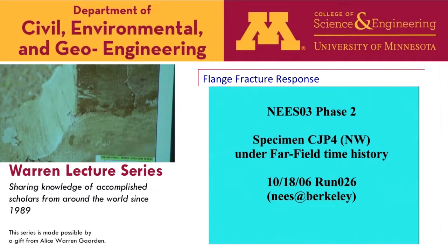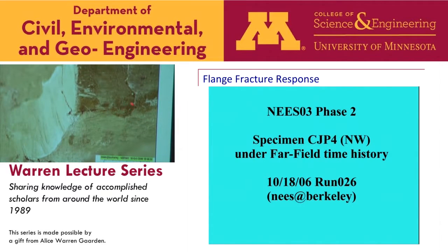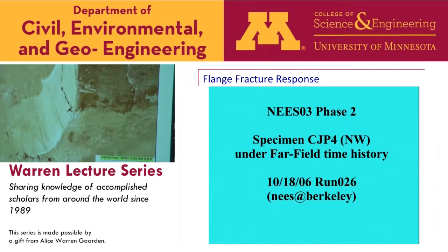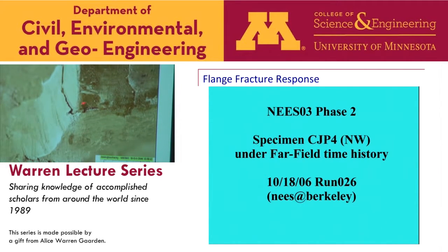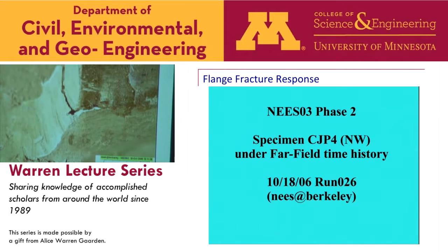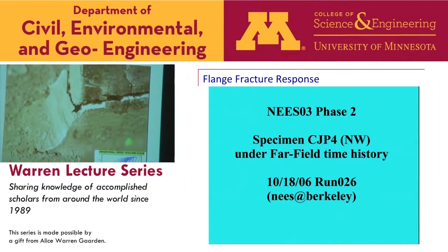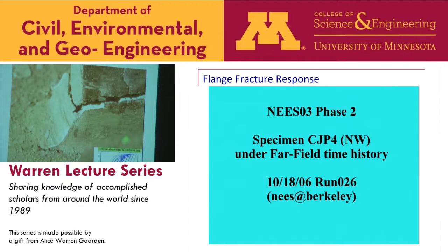But then it does grow to the point, coming up on one of these cycles, where all of a sudden it gets large enough that linear fracture mechanics, or more conventional methods, can make the prediction of at what point this will grow enough to take off and have a brittle fracture. Yeah, and there we go.